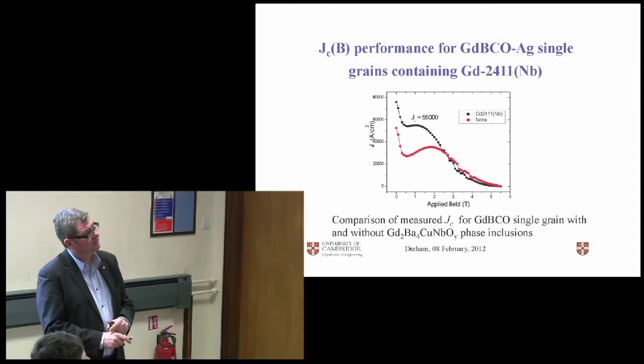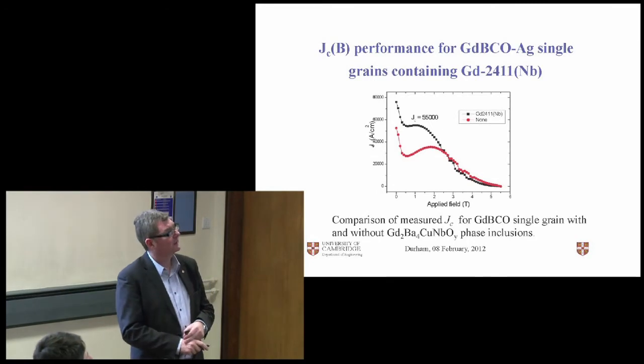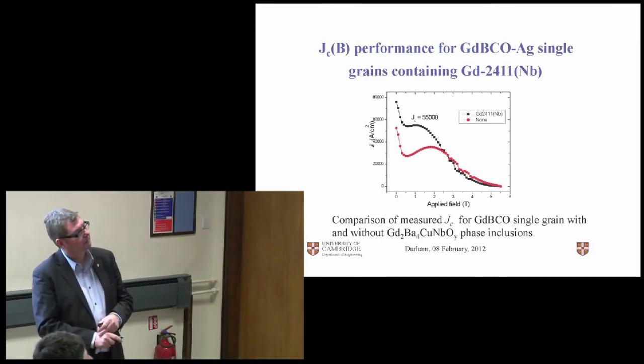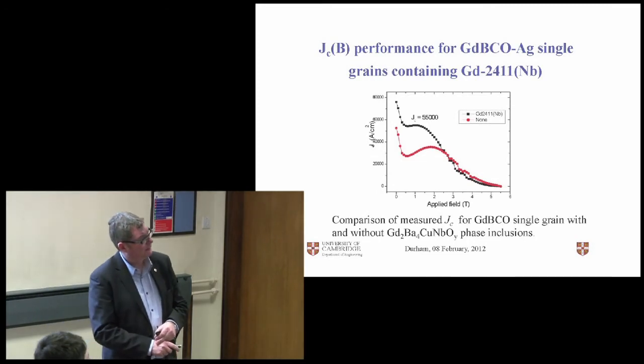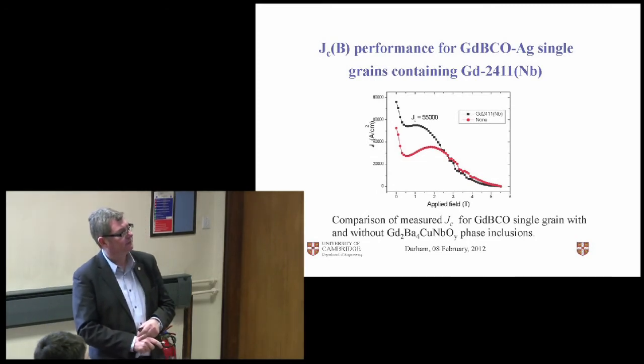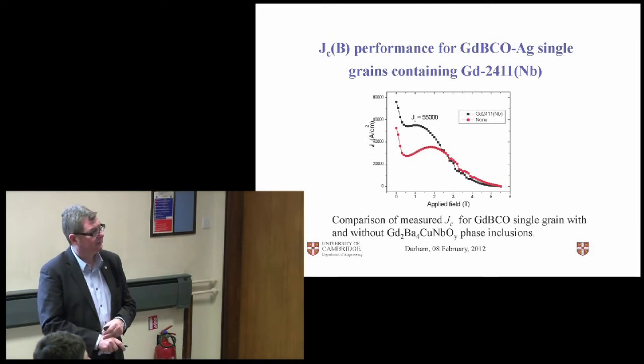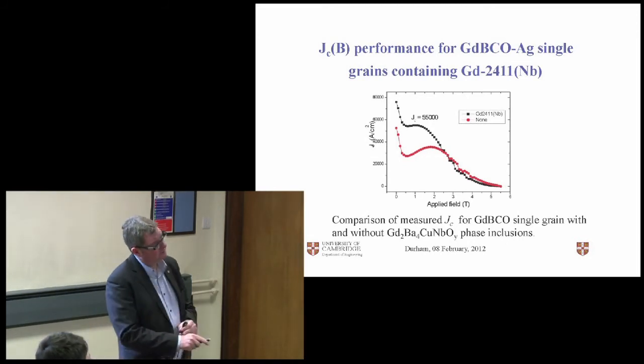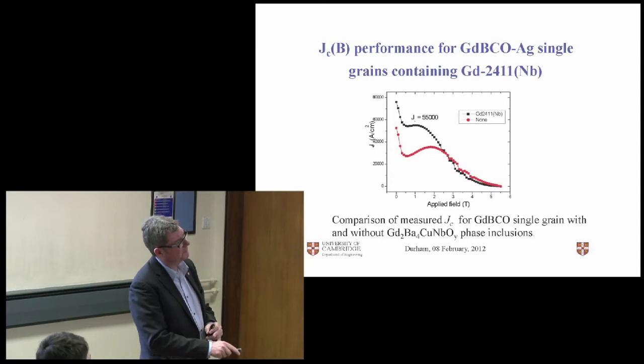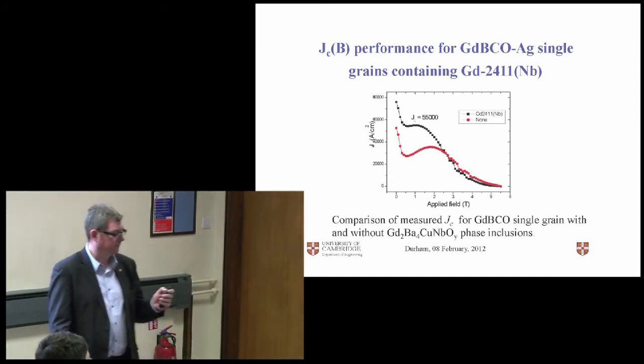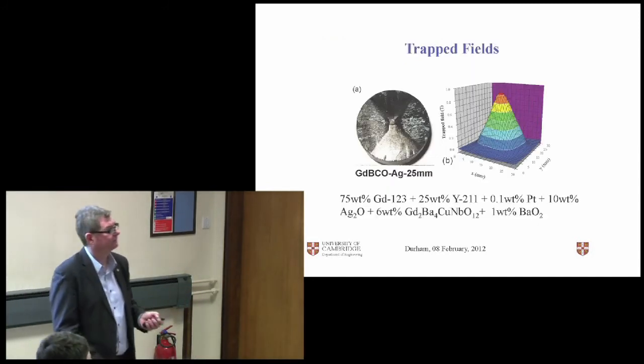Okay, so if we take a single grain, so this is the gadolinium barium copper oxide, we find that silver works best for gadolinium, and if we add the niobium doped 2,4,1,1 variant, we get this big increase in JC, again at intermediate field. So this is a fairly dramatic improvement. So this is suggesting that around about 2.5 to 3 Tesla, these pinning centers become less effective.